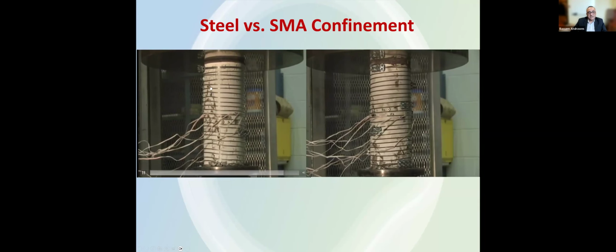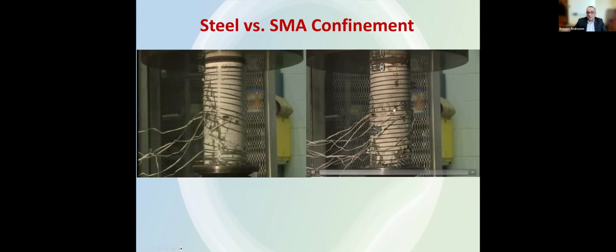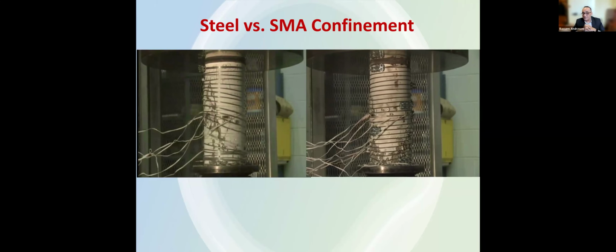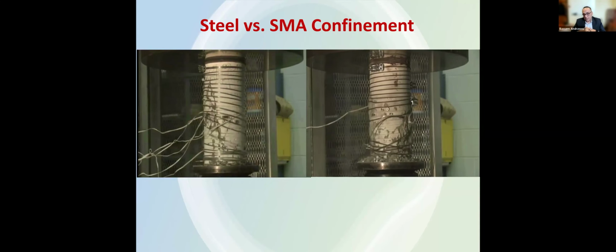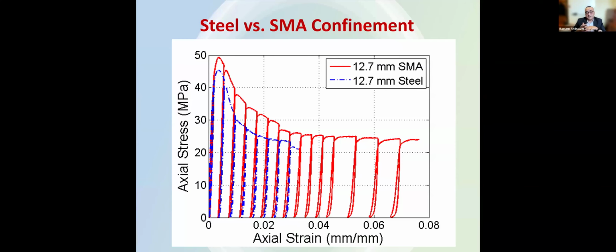See here the shear diagonal cracks forming right away very quickly, and then boom, the fracture of the spiral. While when you look here, I want you to watch the plate on the bottom just compressing, squeezing the concrete here and unsqueezing. It's like a pillow. So before your own eyes, you can see actually the concrete being squeezed. Only a 2 millimeter diameter wire that you are able to wrap with one hand is able to do this to the concrete. By the way, this is not special concrete. It's just regular, normal 4 or 5 KSI concrete. The effect is significant.